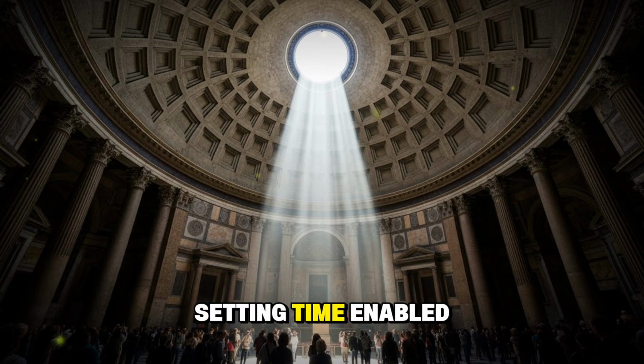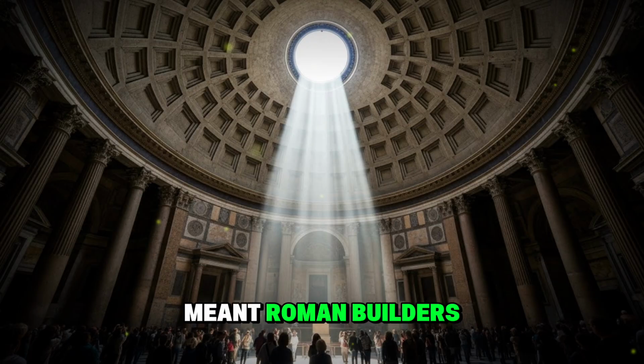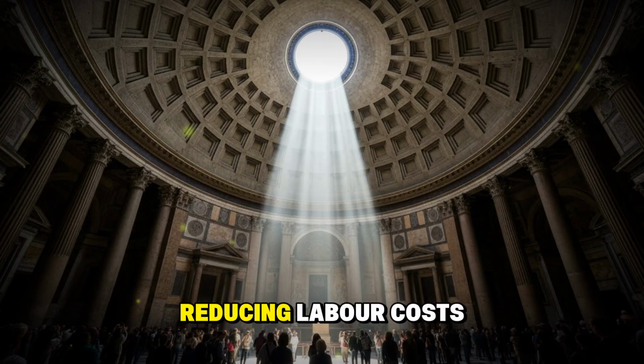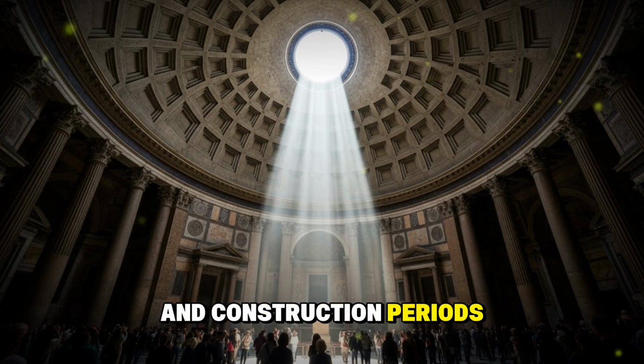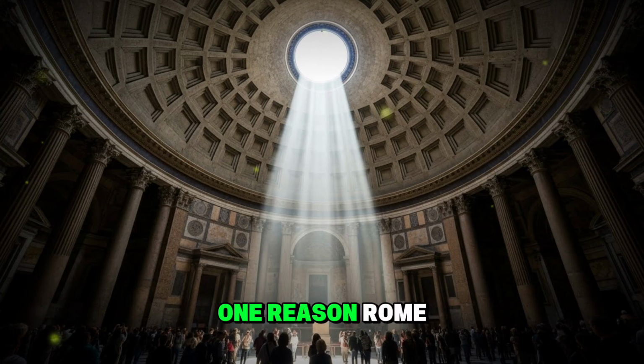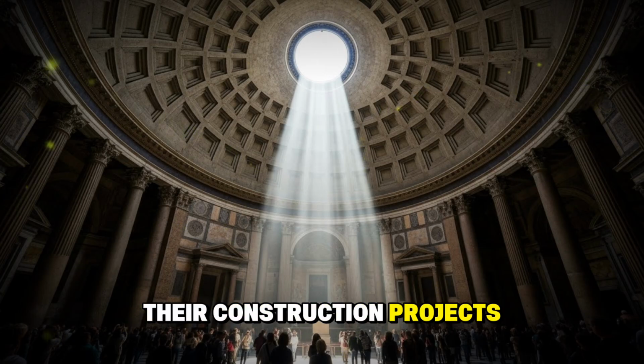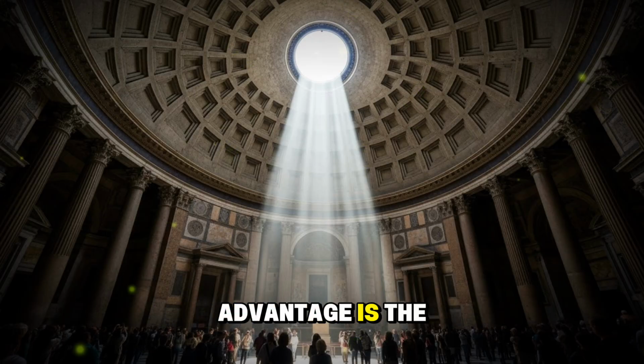Second, the rapid setting time enabled by hot mixing meant Roman builders could work much faster. Structures could be built in less time, reducing labor costs and construction periods. This speed was one reason Rome could build on such a massive scale. They weren't waiting days or weeks for concrete to cure before adding the next layer. They could work continuously, maintaining momentum in their construction projects. But the third advantage is the most remarkable. Those lime clasts, those white chunks that looked like impurities, give Roman concrete the ability to heal itself.